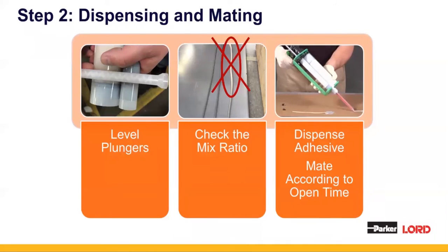Now, if you don't mate your parts in that open time, the adhesive is going to skin over and it's going to result in poor adhesion, if not no adhesion. So that's really important to make sure that you're staying within your open times to ensure that your parts aren't going to come apart, not necessarily just in the oven, but once you have your parts installed in the field. Now, conversely, that works in the opposite direction. For every 20 degrees below ambient temperature, you're going to want to double your open time as well as double your handling time. What that means is actually leaving your parts clamped longer so that you're building enough handling strength before you go into the oven.